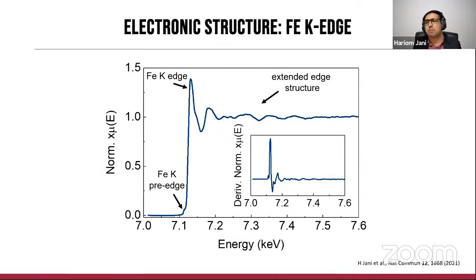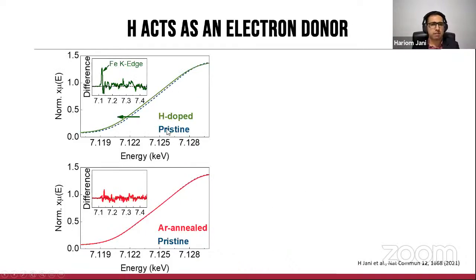So we observed that apart from various other factors, the key factor that is changed by hydrogenic doping is really the electronic structure. And to convince you of that, I'm showing you here the K edge of the iron in these samples, predominantly focusing at the main rising edge in the system here. Now, what we observe is that in comparison to the pristine state, when we put hydrogen, there is actually a shift towards lower binding energies in the system,